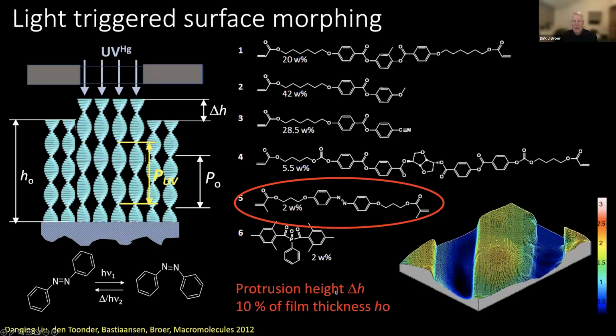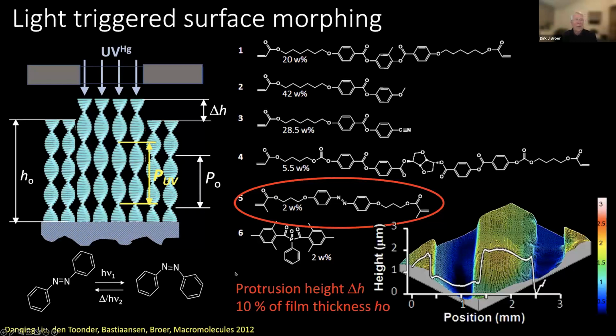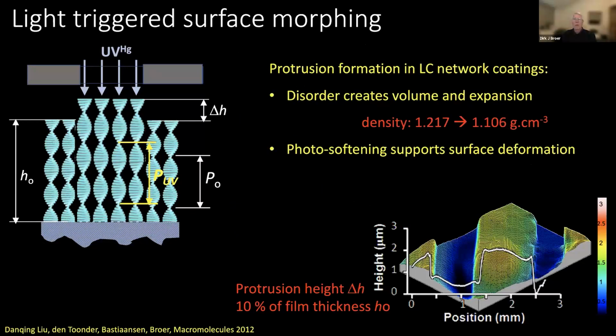The protrusion can be actually as high as 10% of the film thickness, which means that if you have a 10 micrometer thick film, you create topographies which are in the order of 1 micrometer, as can be seen here. And it is reversible. If you switch off the light, the system goes back to the trans state again, and the protrusions disappear again. This all on a time scale of several seconds. Well, the mechanism behind this is that the disorder creates volume and expansion. That means that the density is reduced in this case from 1.2 to 1.1, and more or less corresponding to the 10% in expansion here.